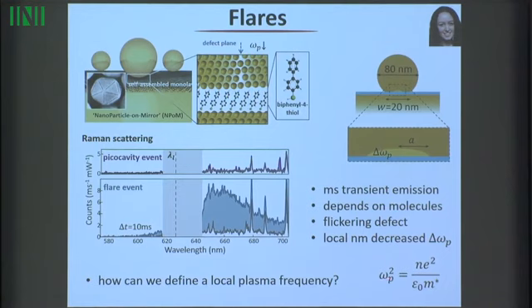So the plasma frequency is essentially how we think about electrons sloshing around inside the gold. And we normally learn it in undergraduate. It just depends on the density of electrons and their mass. So it's normally considered a fundamental for any particular material, for metal, say. But here, what it looks like to us is that this plasma frequency of this small region here, which is a couple of nanometers across, is actually much, much less than the plasma frequency of the bulk metal.